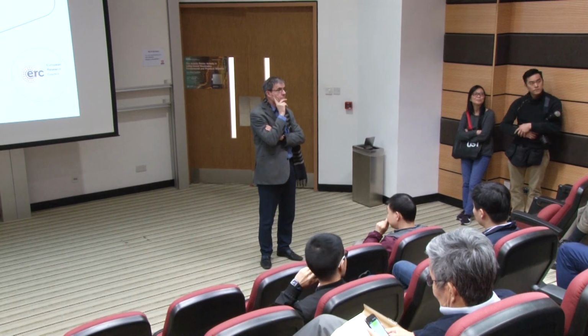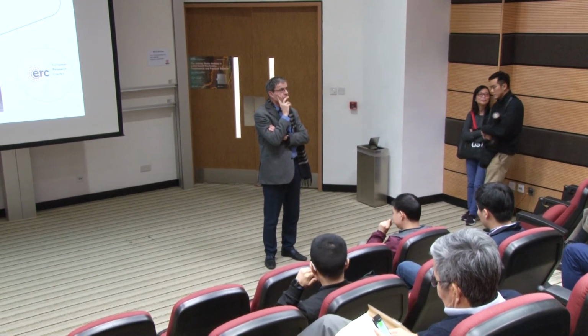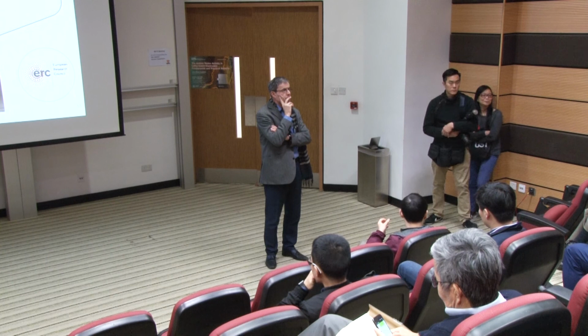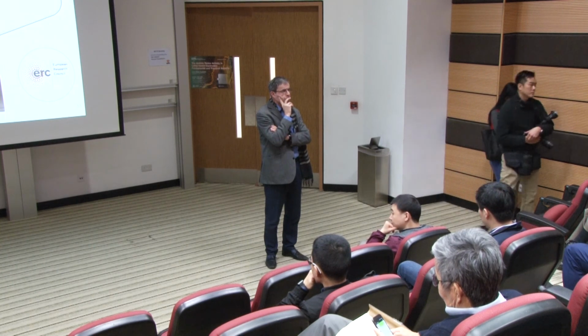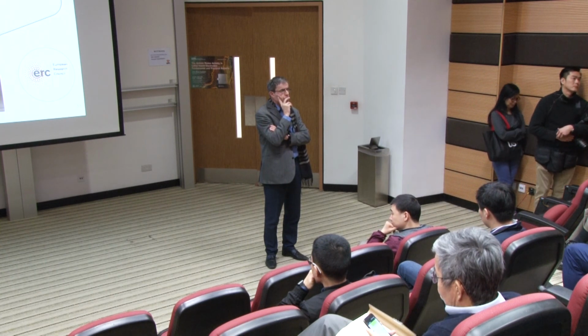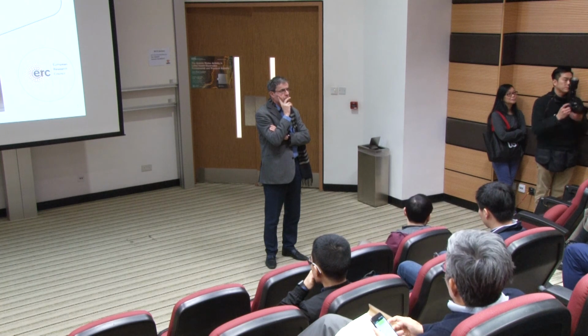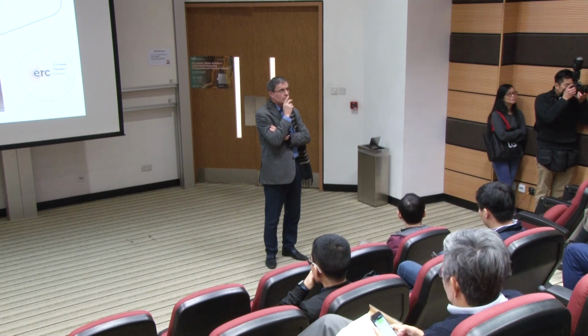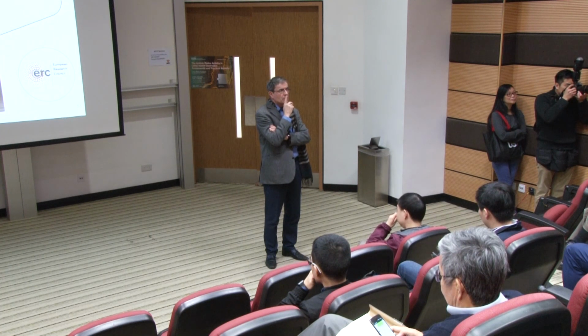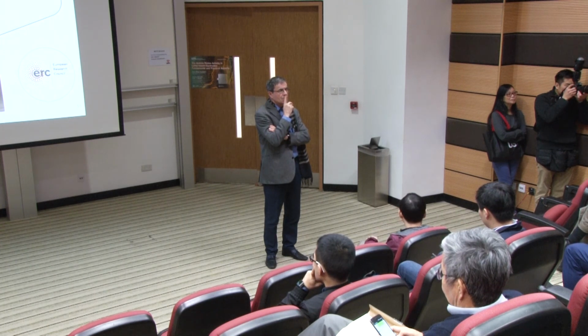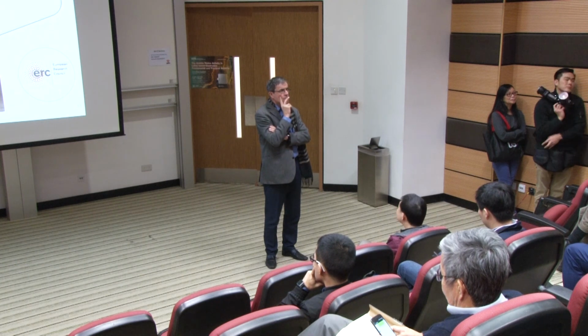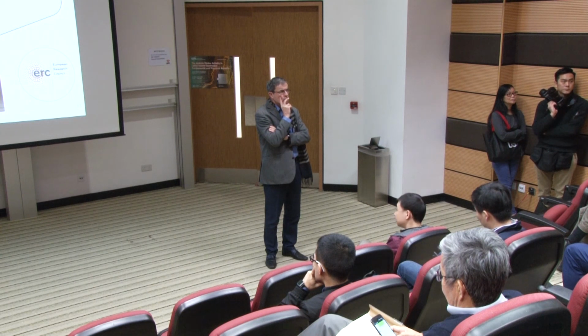Thank you, sir, for your wonderful talk. Sir, I have one question. For your lithium, ruthenium, titanium oxide material, you have shown that the voltage hysteresis, which you are mentioning about, has not been solved to a great extent. But when you replace the titanium with tin, then the voltage hysteresis got reduced. So what is the reason that in case of titanium there was large hysteresis, and for tin, there is low?